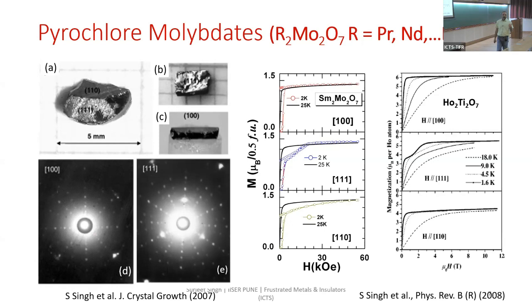And second, molybdenum oxide is highly volatile. So around 1200 degrees centigrade, it starts evaporating. So we had grown these crystals, and